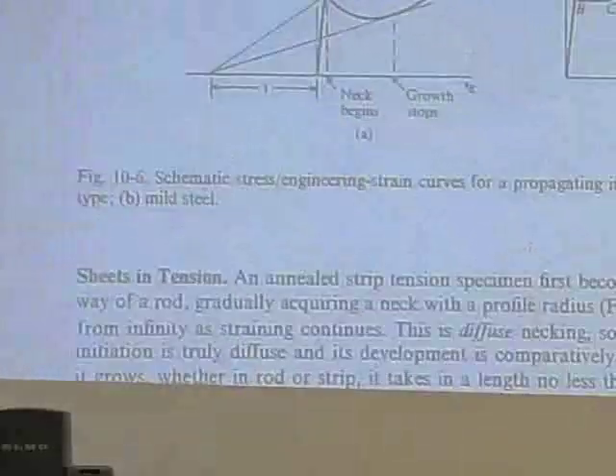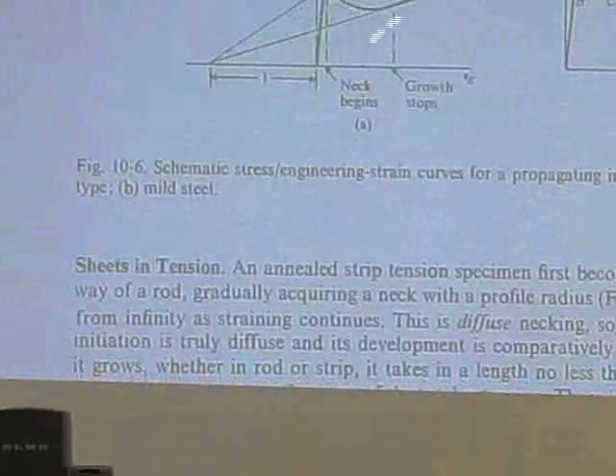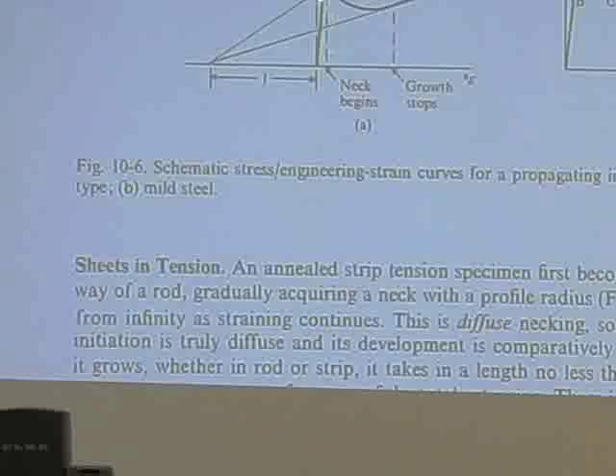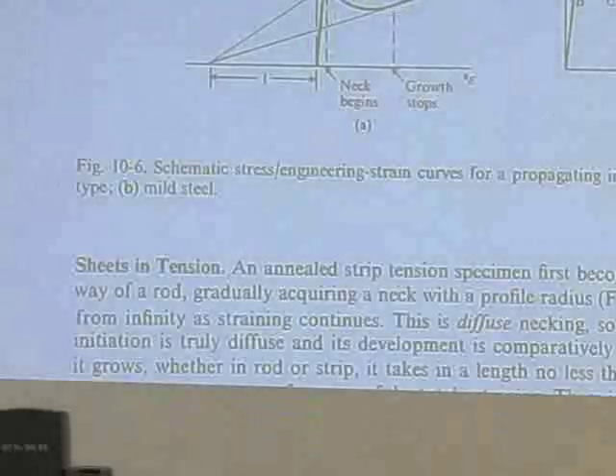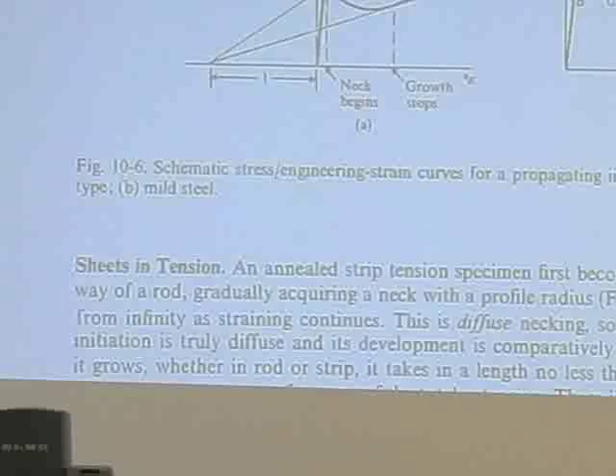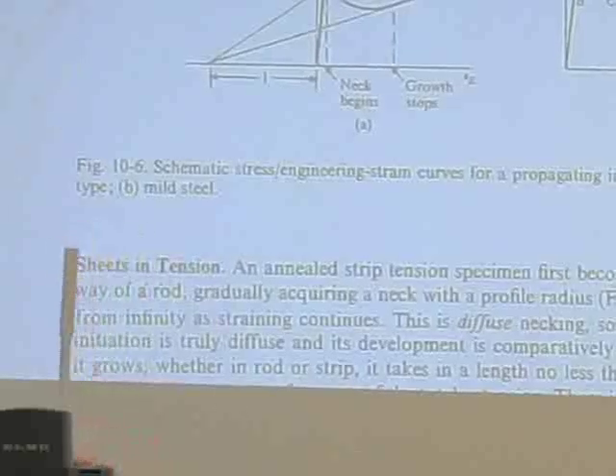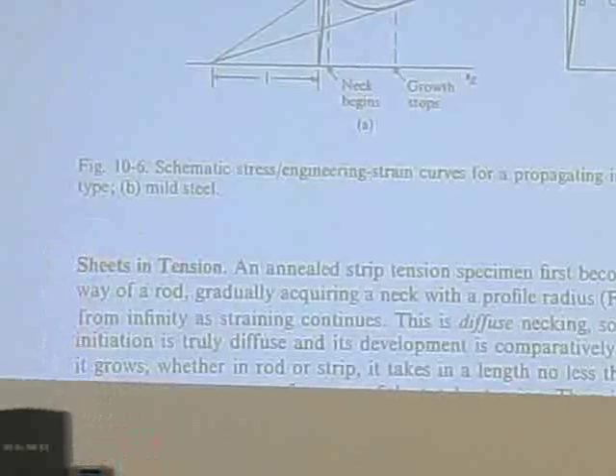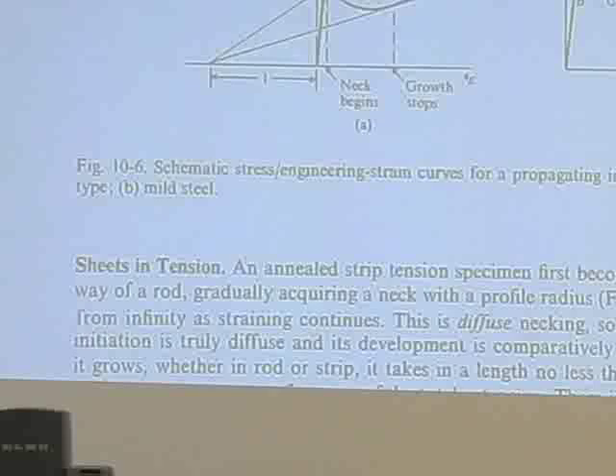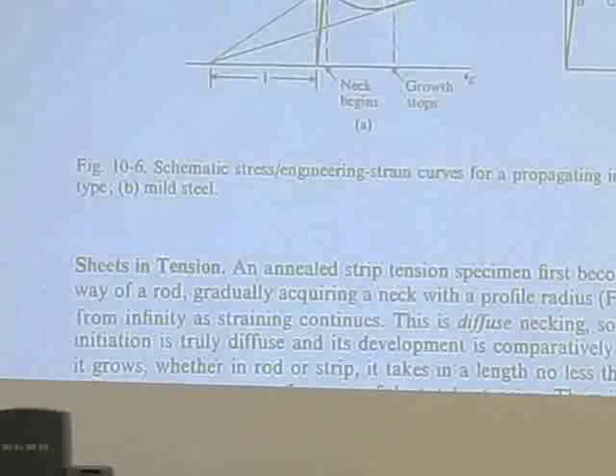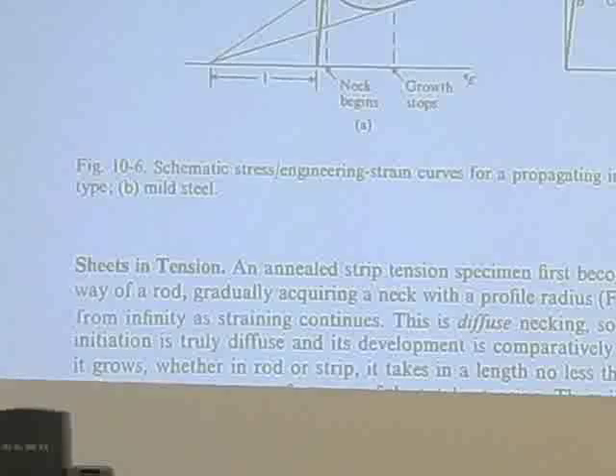Now, in the real world, stress strain curves are not always so well behaved. And sometimes, anybody know what type of material typically gives you a stress strain curve that reaches a max, then drops, and then increases? Polymers. A lot of your polymers. Polyethylene, polypropylene. Polyethylene being this, okay? It will typically have a stress strain curve where it first yields, and then as everything's starting to move around, it decreases, and then as you start getting all these chains aligned, now you're starting to get the modulus of the chain as opposed to the van der Waals bond in between the chains, and the thing will take off. And so you get a dip.